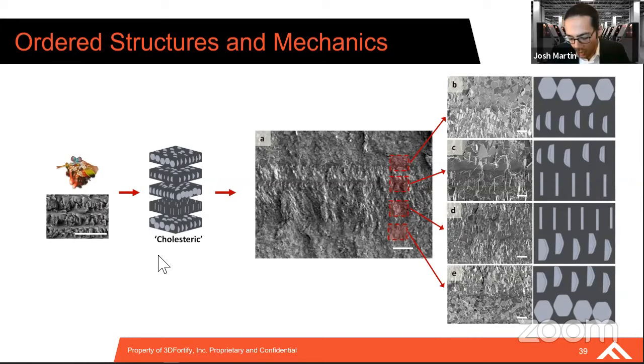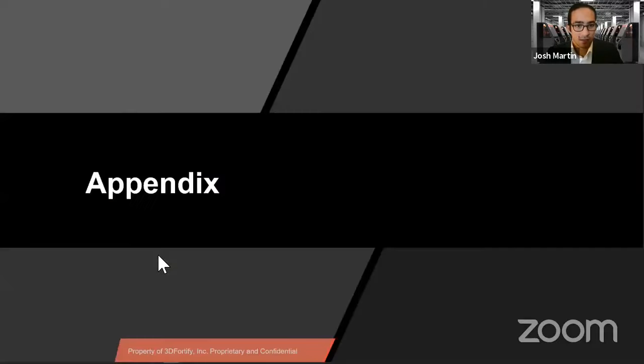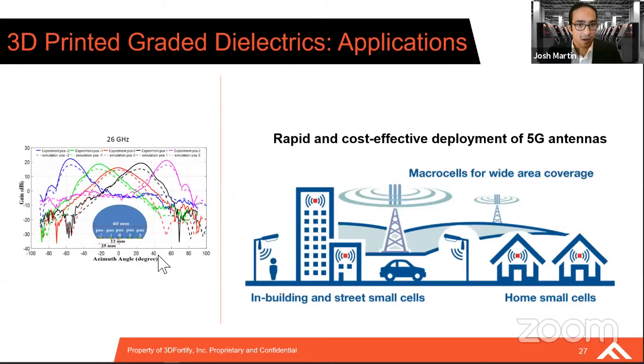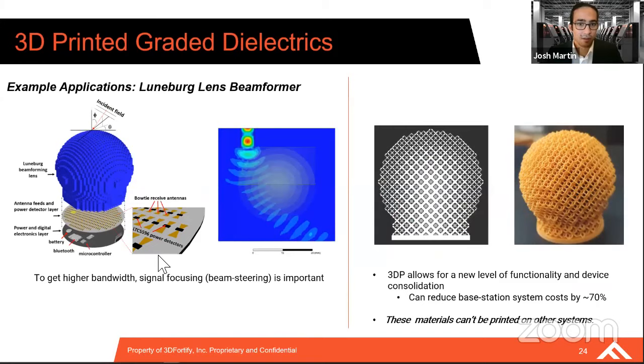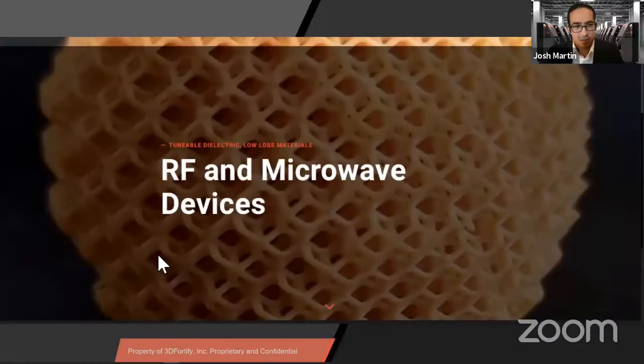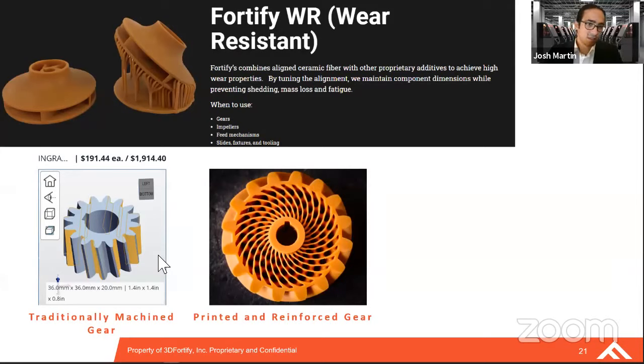Right. I wish I could give you a very binary or discrete answer. It's a function of the surface area of your particles. If they have a really high aspect ratio, your system will get more viscous much more rapidly. Just to give you a few examples, if we look at what we're doing in this RF space, these materials are essentially half additive by volume, so it's pretty high loading. And we're talking about viscosity in almost the 10,000 centipoise regime. It's like honey. And if we look at some of these other examples, these high wear resistant materials, we have an additive package that's closer to 15 to 20% by volume.